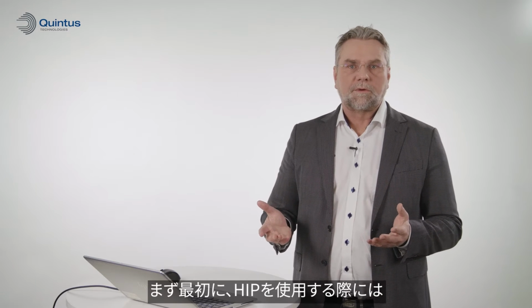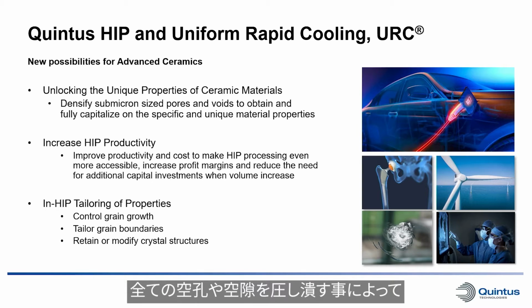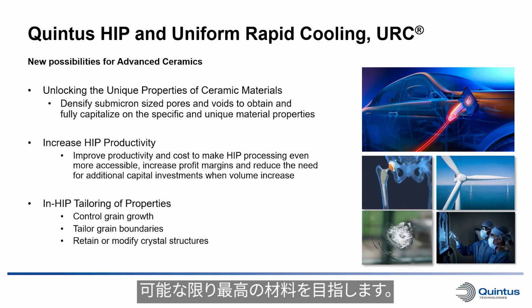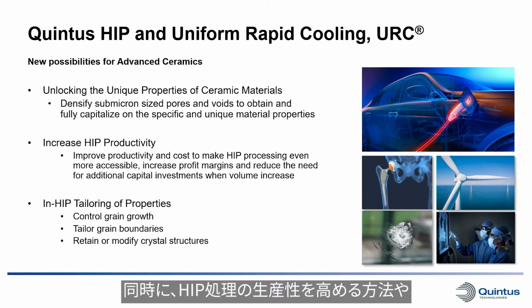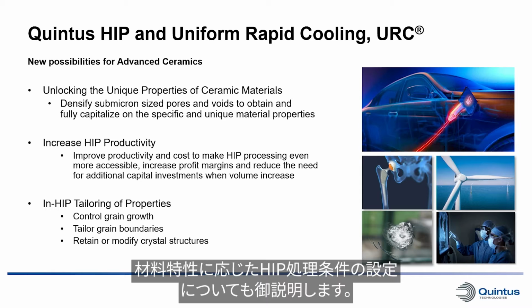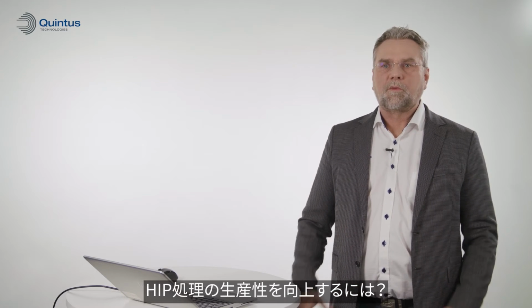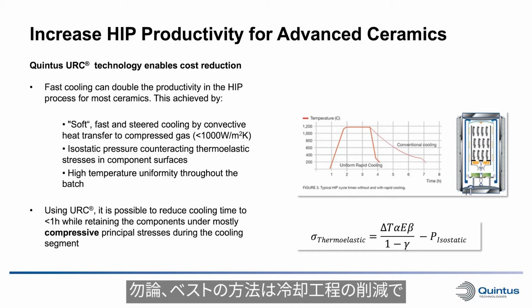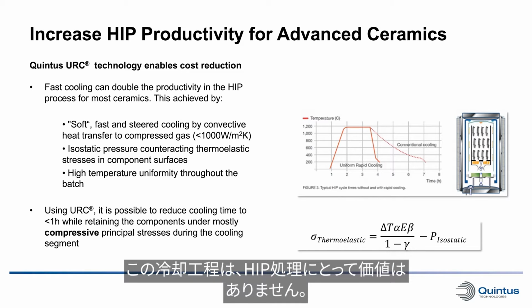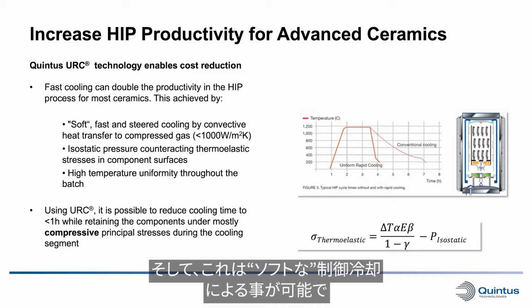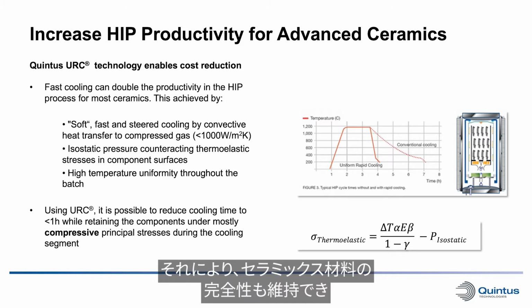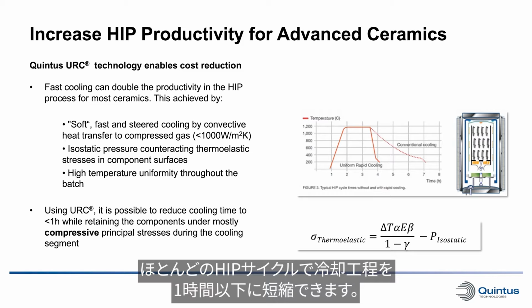So the first thing, of course, when using the HIP, is that we want to make sure that we get the best possible material by closing all the pores and voids. But now we also want to look into how we can increase the productivity when hipping, and also what can be done when it comes to in-HIP tailoring of material properties. How do we increase HIP productivity? Well, of course, the best thing is to reduce the cooling step, which gives no value to the hipping process. We can do this with a soft steered cooling, which will allow us to keep the integrity of ceramic materials and bring the cooling step to 1 hour or less for most hipping cycles.